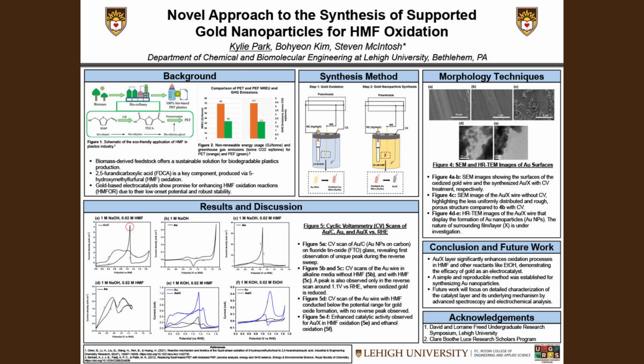For both setups, a mercury-mercuric oxide reference electrode, platinum wire counter electrode, and gold wire working electrode were used and run under chronoamperometry, 2.4 volts versus RHE for 10 minutes. The first step of gold oxidation was conducted in 2 molar potassium hydroxide solution and resulted in a reddish-brown color change. The second step, gold nanoparticle synthesis in 2 molar potassium hydroxide with 20 millimolar HMF, turns this oxidized gold wire black immediately, and we identify this black layer as AuOx.